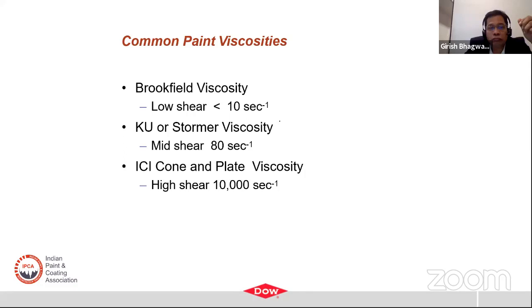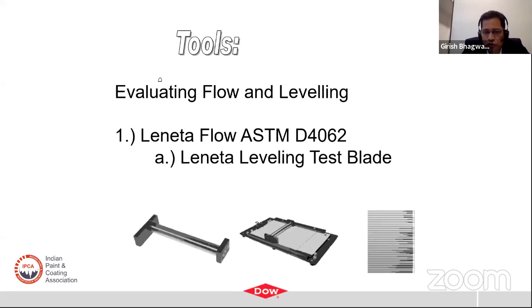We measure the low shear viscosity using a Brookfield viscometer, at 10 second inverse, which is as low shear as that. Then you have the Stormer viscosity, which is measured to check that when we are delivering the paint in the can, it will not lead to any kind of settling, etc., and for pick up on the brush. So mid-shear viscosity is like 80 second inverse, and the ICI cone and plate is 10,000 second inverse, especially for brushing, rolling, etc. So we don't have to get into these jargons because it's a little bit complicated, and many of them will get confused. So eventually, what it means is, you should not have problems when you apply it on the wall.